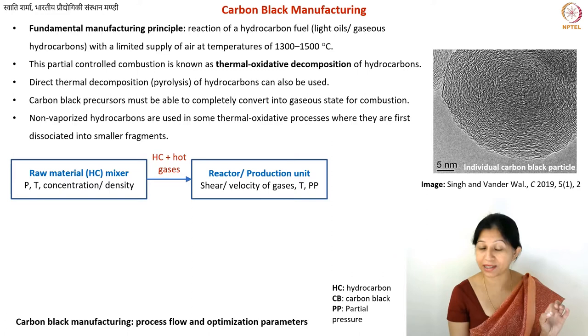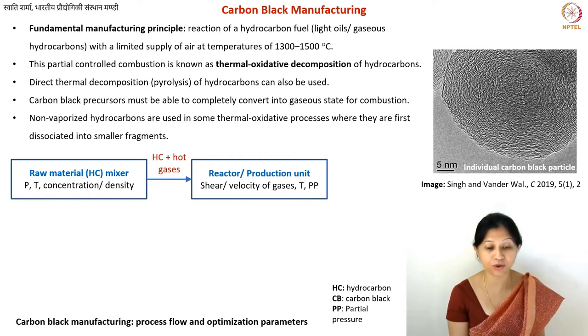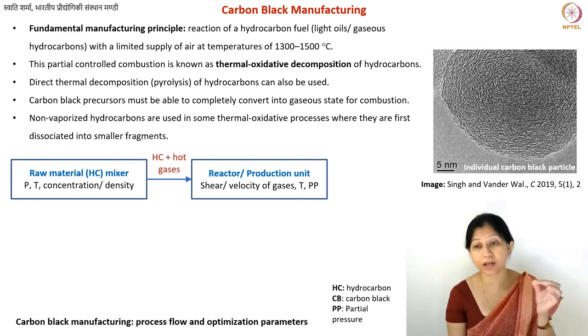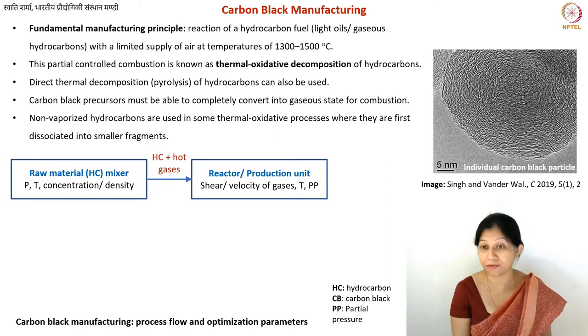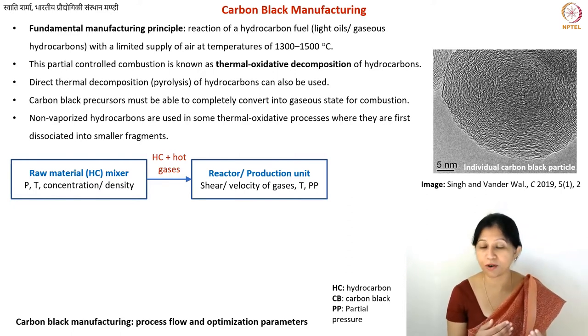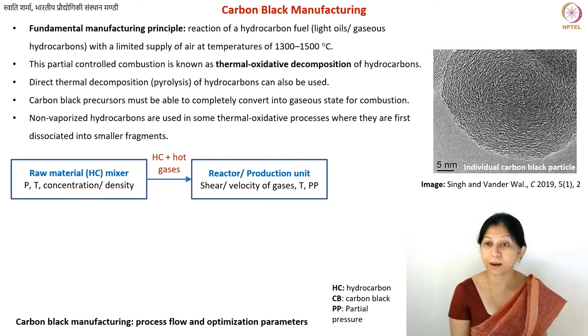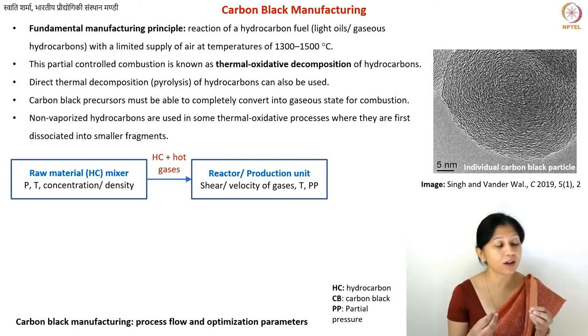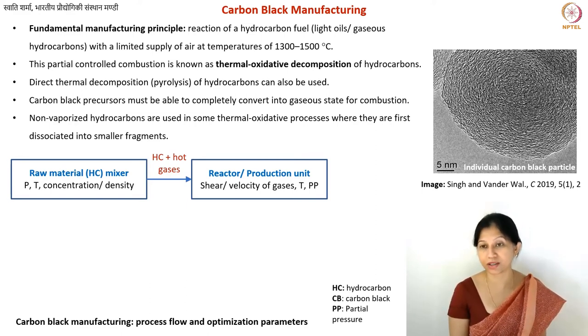In the reactor, you have burning — combustion taking place. You need sufficient oxygen or air supply, and you need to ensure the correct partial pressures of gases, because you are supplying air and forming carbon dioxide and carbon monoxide, along with flue gases. You need to ensure that the partial pressure of all these gases is optimized so that you have optimum combustion while still forming solid carbon particles, and not all carbon is converted to carbon dioxide or carbon monoxide.